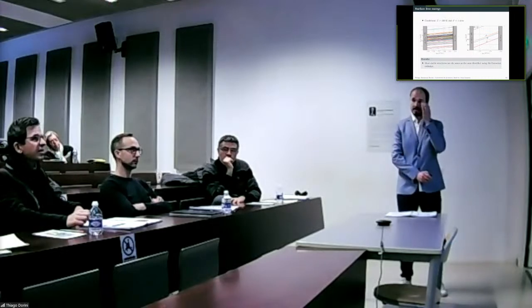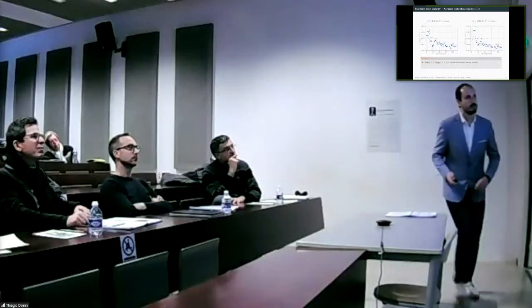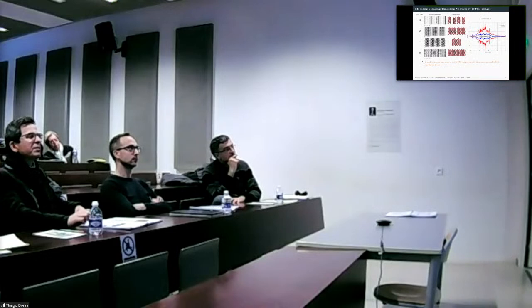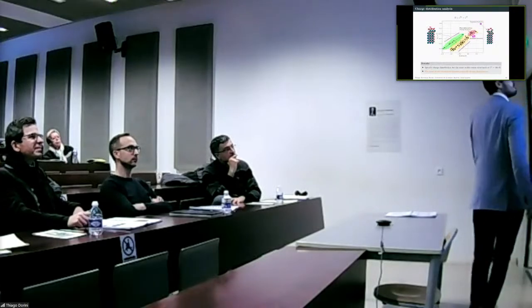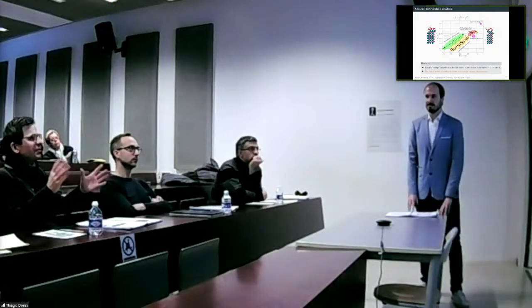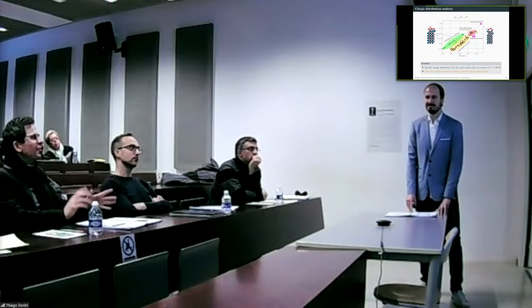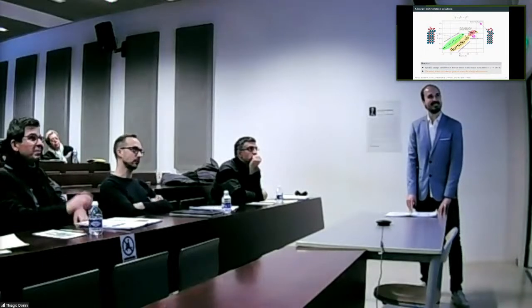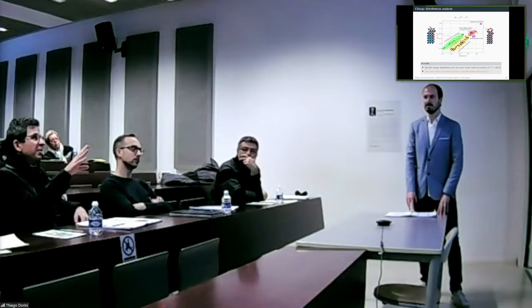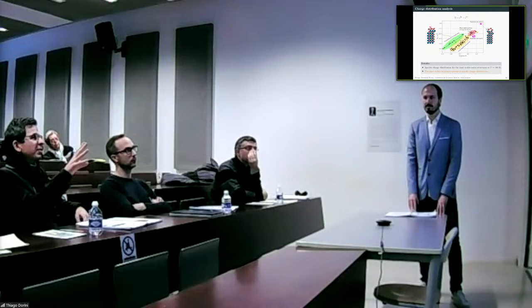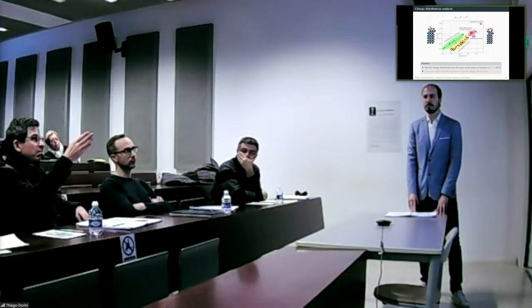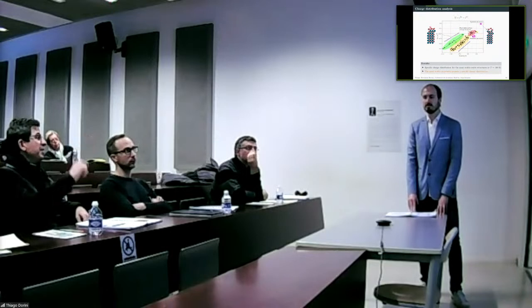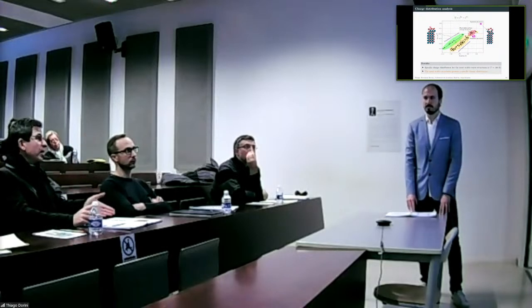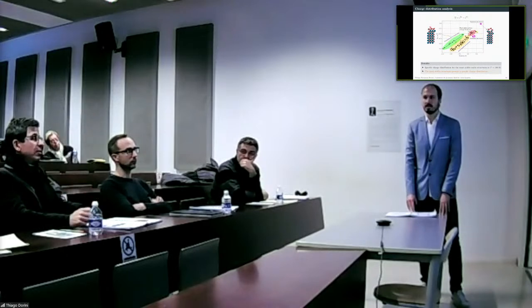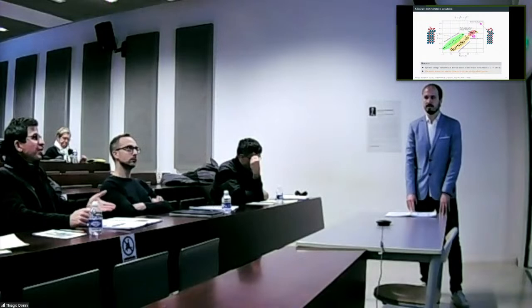But let's have a look at your final figure because I like it very much. The one where you show this one. The one before, sorry. It's very synthetic, and you get an overview of all the systems. I like it very much. But it also shows that for some reason, the large majority of your structures are not stable, because they produce a rumpling that is negative and large, and charge transfer to the palladium substrate that is much too large. Exactly. So where does this large charge transfer come from?